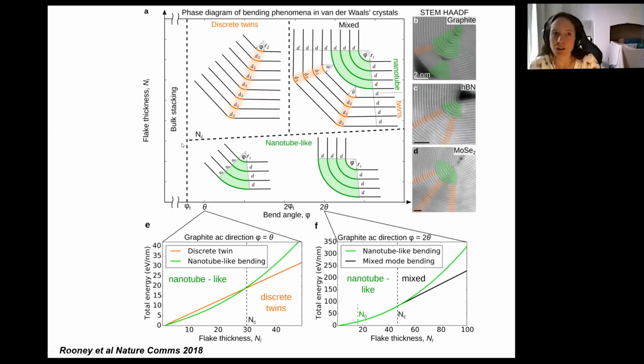Now, that is really important because we find that we get this critical thickness, and this critical thickness corresponds to the thickness at which it is very hard to get mechanical exfoliation and liquid phase exfoliation to work really well. And so we've got some follow-up work, which I can't talk about because it's not published yet. However, that's really encouraging, and it seems to be giving us some really exciting insights into the efficiency of liquid phase and mechanical exfoliation, and how this depends on the ability of the crystal to form twins.